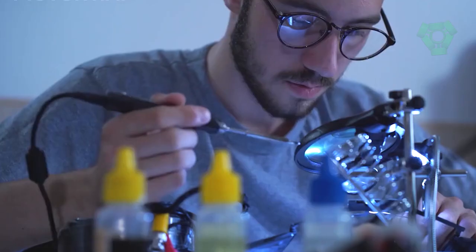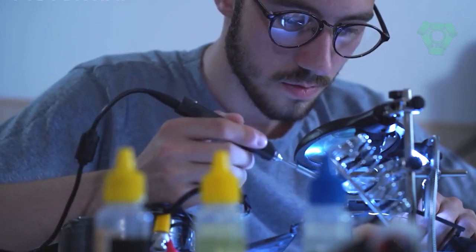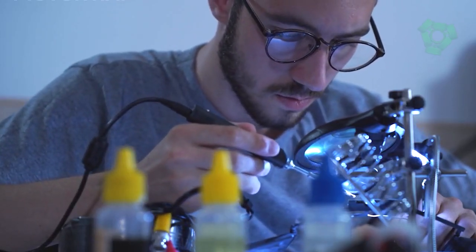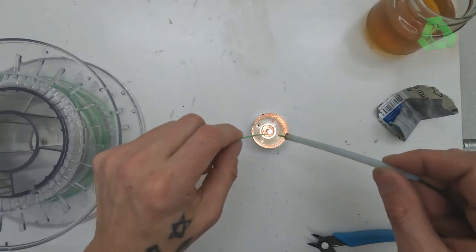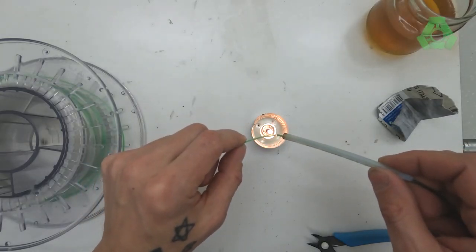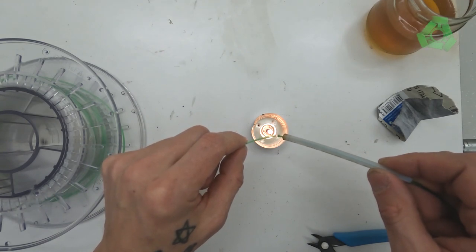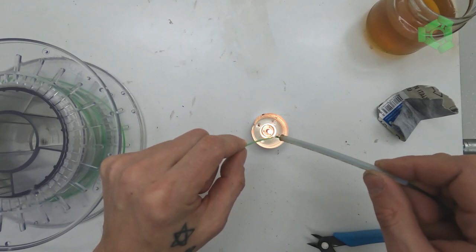Make more filament. Weld filament. As each bottle will only produce a short length of filament, they must be welded together so that your 3D printer can print a whole or multiple archipelago islands. Insert one of the ends of the filament through a length of silicone tube with an inside diameter of 1.75 millimeters to 1.8 millimeters and position it close to the end of the filament.